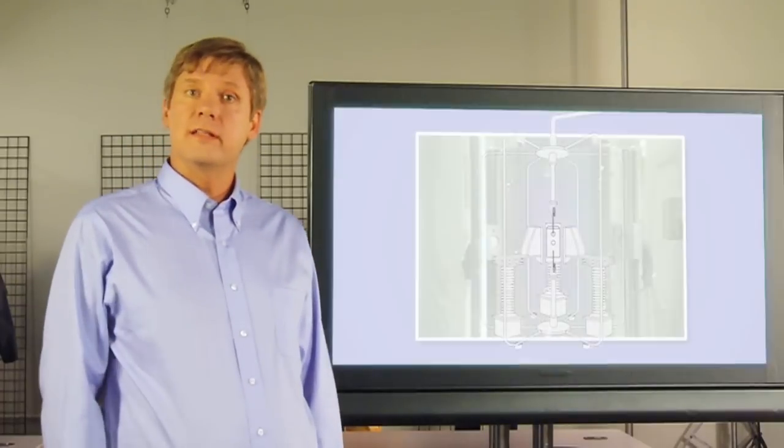Now let's take a look at this test being conducted. This particular test shows a sample of FR fabric being tested. The arc flash is created and you can see the intensity and the discoloration of the fabric due to the extreme heat. After performing and analyzing the data from many tests, an arc rating for this fabric is established.